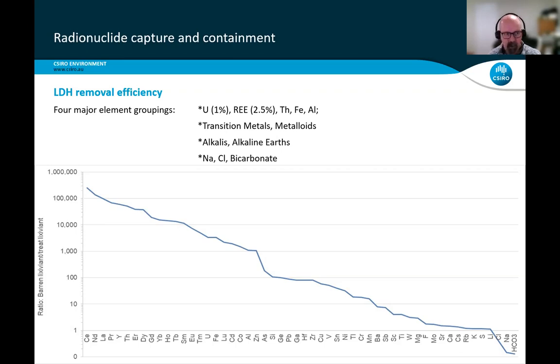And on the x-axis there, what we've got, I've ranked the elements according to their removal efficiency, and I'll talk about that now. So we have 4 natural groupings there that actually fell out of this. The first grouping contains uranium, and we had about 1% uranium in this layered double hydroxide precipitate, around about 2.5% rare earths. And then we also had thorium, iron, and aluminium. So if you look now at that x-axis, you can see a whole lot of rare earths, cerium, neodymium, lanthanum, praseodymium, and the like. We can also see thorium, uranium, and also a couple of trace elements in there, things like cobalt and cadmium, as well as the Al. But predominantly uranium and rare earths and thorium and aluminium and iron.